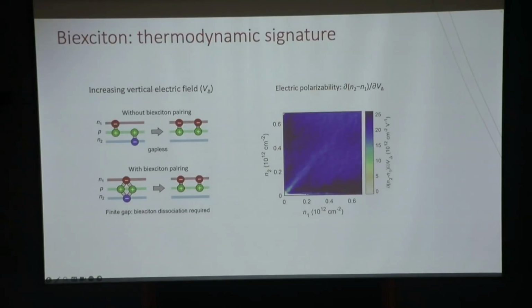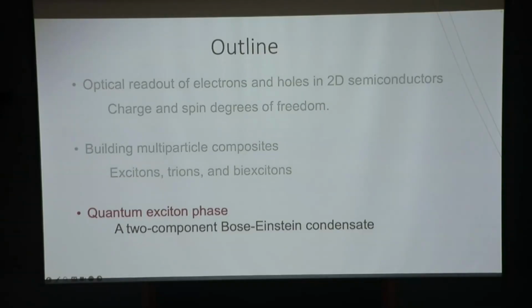Experimentally, we can obtain this compressibility of moving one charge from the bottom layer to the top layer versus this vertical field. And what you can see is there is an incompressible region in the middle, when the two types of excitons have exactly the same density. They all form bound biexcitons. Okay, so I hope I've convinced you that with this system, we can engineer different composites.